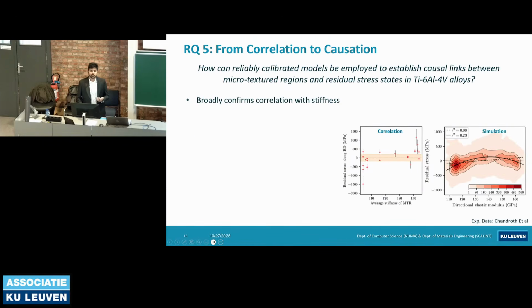But then we had to use an equilibration, and this had to be done iteratively because there are surrounding grains. If you initialize it in just these grains, then it would be incompatible and the volume would not be in equilibrium. So we had to equilibrate it so that we iteratively achieve the experimentally characterized residual stresses in these 28 grains. But the surrounding grains now all have a residual stress because of accommodation of the residual stresses in these grains. Okay. Thank you.